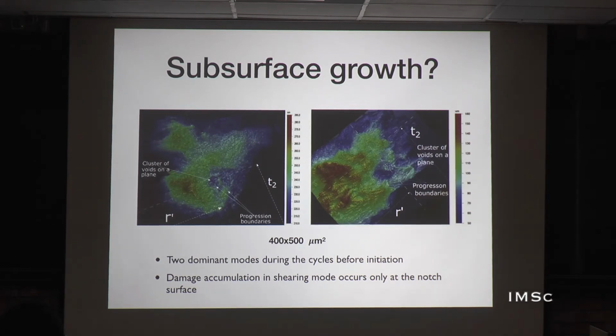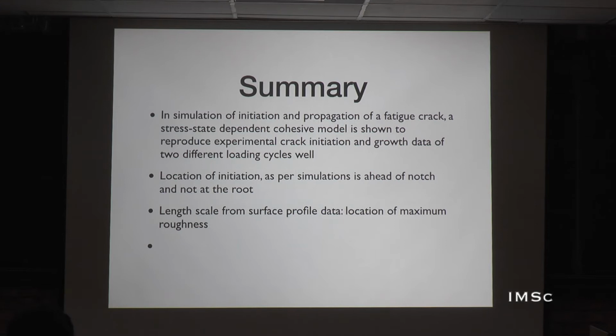Why this happens is because near the surface you have low triaxiality, which encourages strain localization, like we have seen even for ductile fracture. You have slip-based activity taking place, but stresses are higher subsurface, and triaxiality is higher subsurface. So if fatigue damage is dominantly due to triaxiality, you will observe a subsurface planar region which is in opening mode. And so that is the summary.